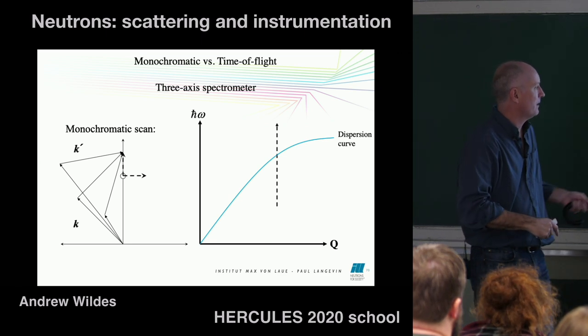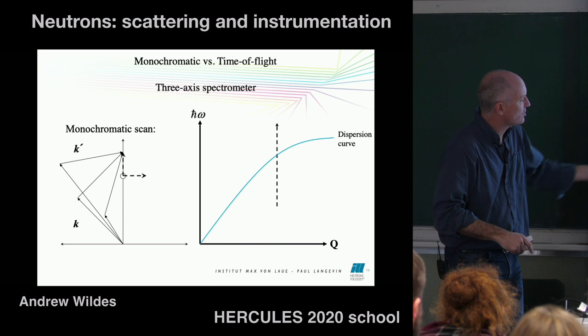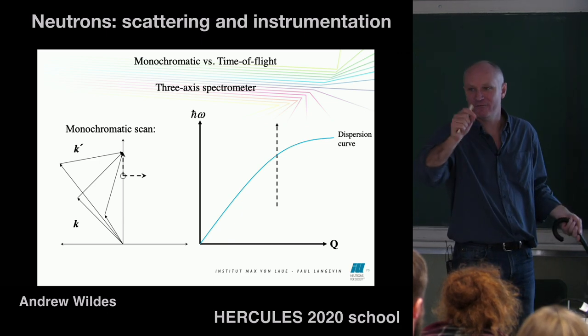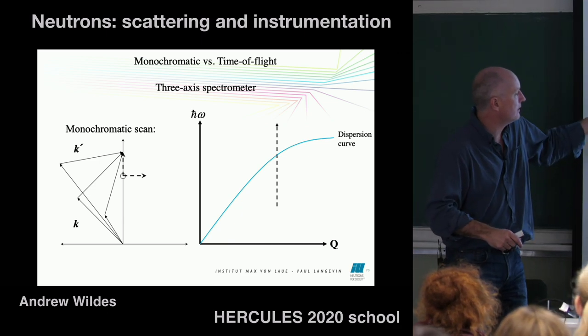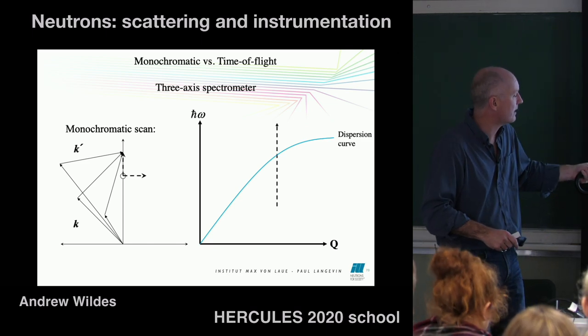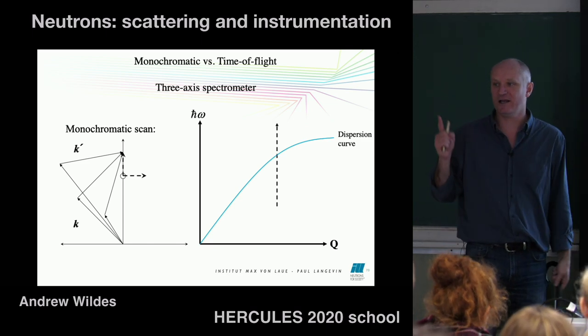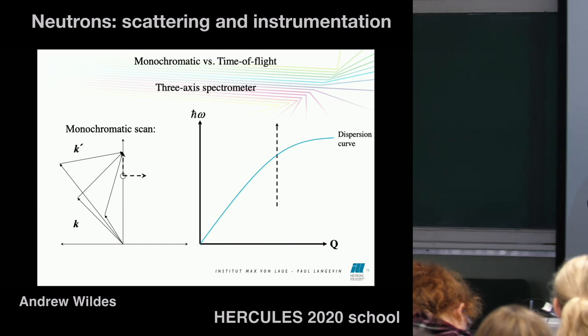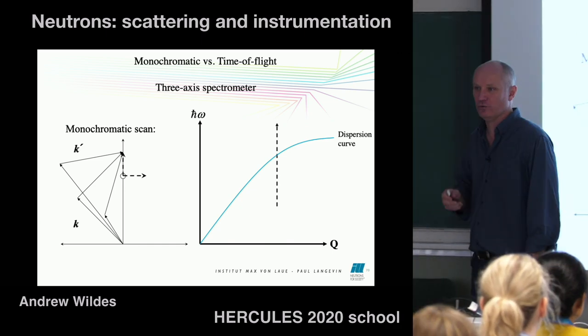But if you do that, in this sort of situation here, you change all these vectors correspondingly, Q is always fixed. Q is always the same, and what you're varying there is only the energy. So you've done an explicit energy scan at a fixed Q.